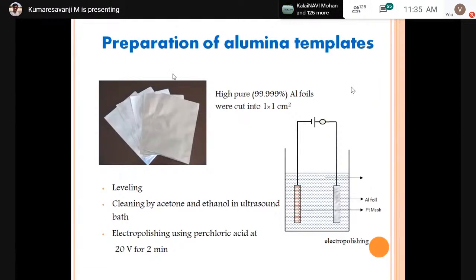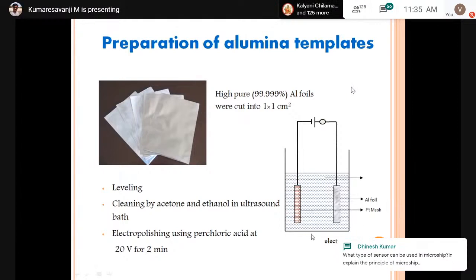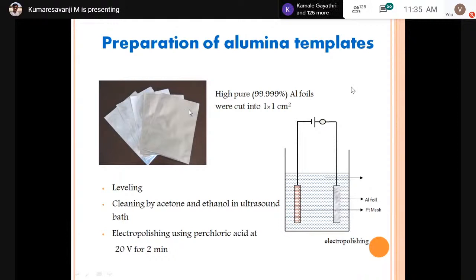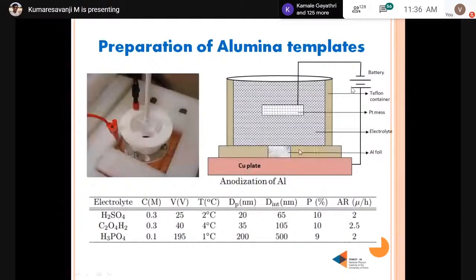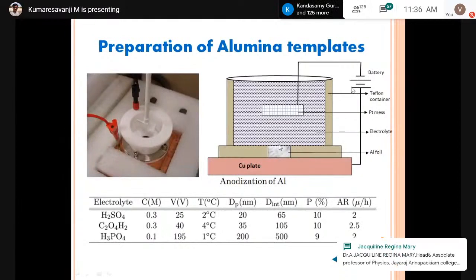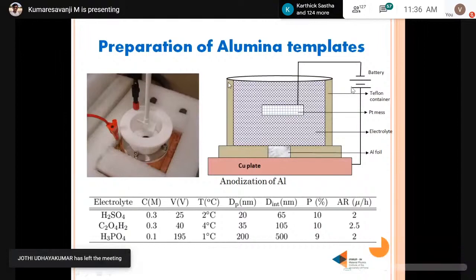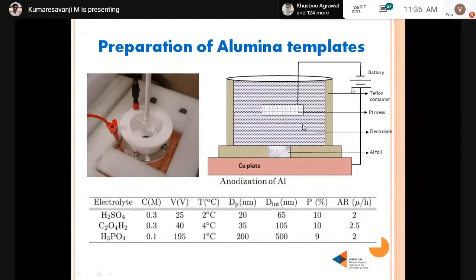Here I show the electropolishing setup. After you do the electropolishing, you will get a mirror surface on the aluminum foil. Then the aluminum foil is fixed in a Teflon cell, which is made in our lab, actually a homemade setup. So in the Teflon cell, we just fix the aluminum foil. Then we fix the copper plate at the bottom. Here you can see a small portion of the hole. This is the aluminum foil, which is attached with the copper plate. Then we attach both, and your copper plate acts as the anode, right? Then we place the platinum mesh and we pour in the electrolytes.